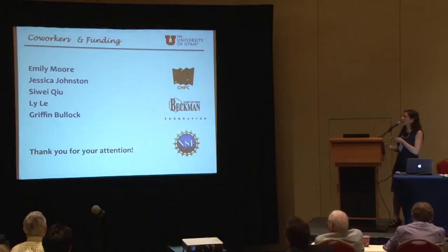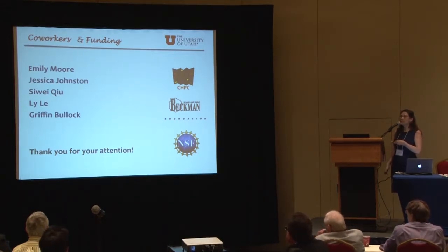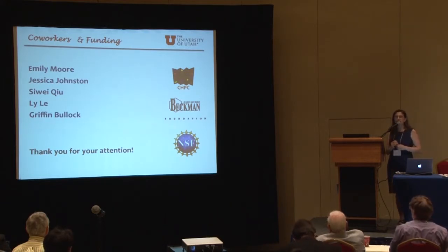Something I didn't discuss: the domains needed to grow ice must be larger than the critical nucleus, and experiments in protogels — solutions with ions fixed — show you need at least two-nanometer-sized water domains to crystallize water. If you constrain water in smaller sizes, it may not be able to freeze. I'd like to thank my co-workers: Emily Moore for bulk water and ice freezing; Jessica Johnston for nanoparticles and stacking-faulted structures; Ly Le for glass formation and nanosegregation; and Griffin Bullock for crystallization of solutions. Supported by the Beckman Foundation, NSF, and the Center for High-Performance Computing.